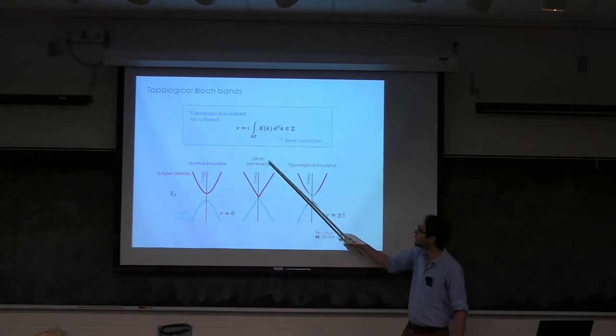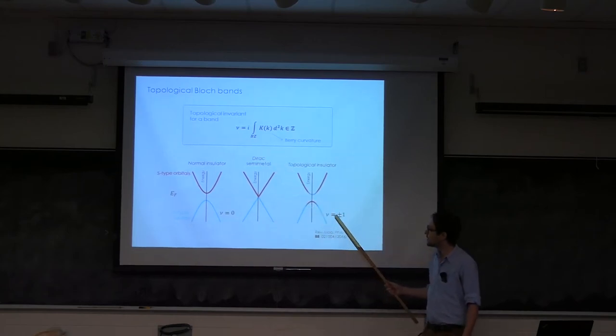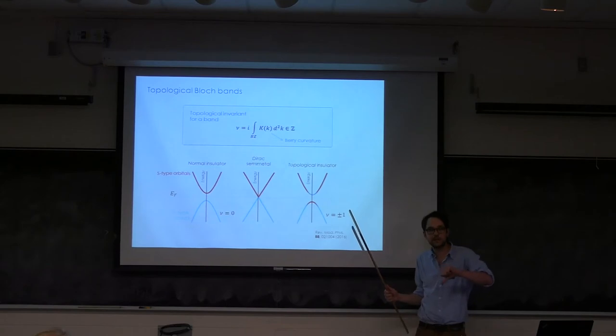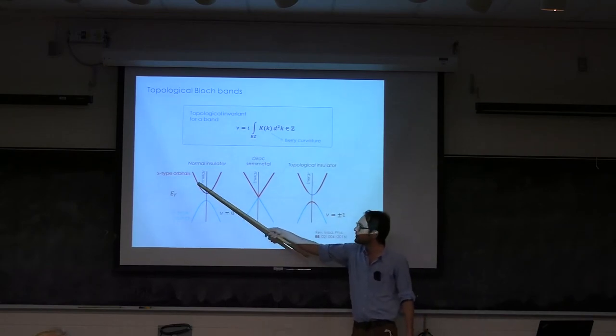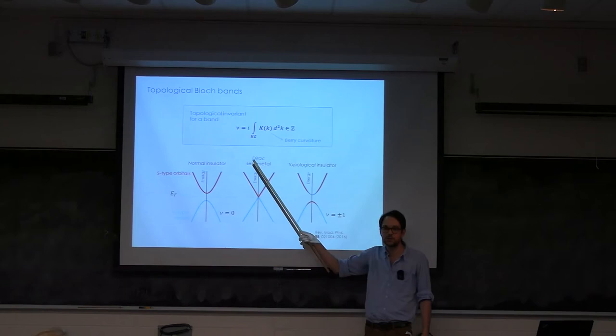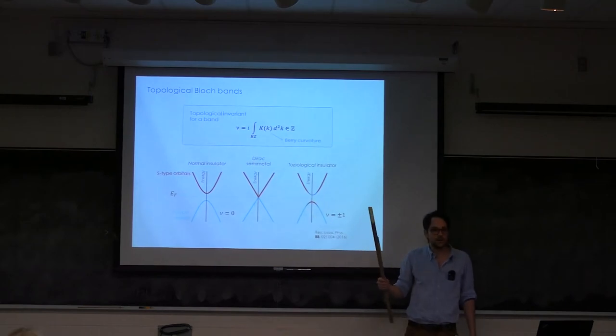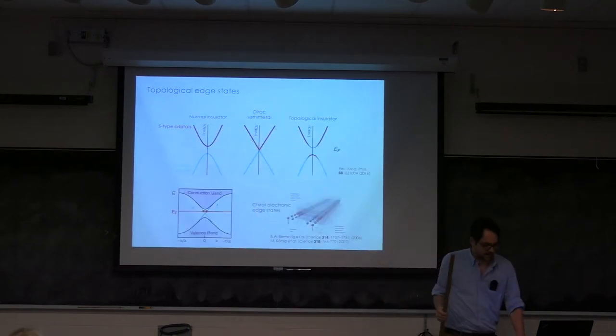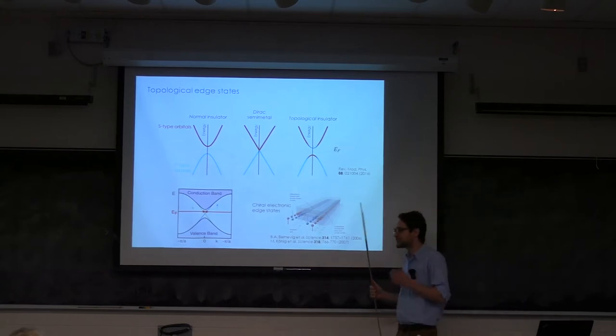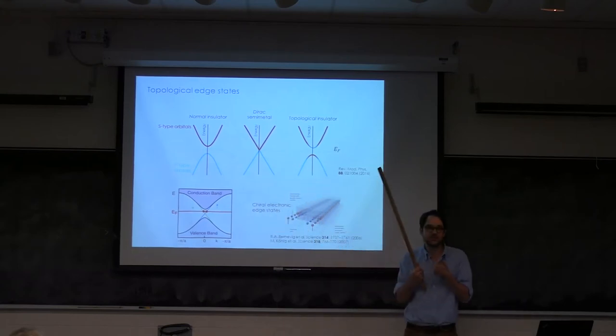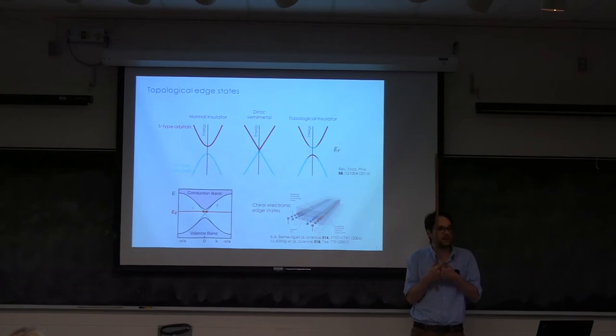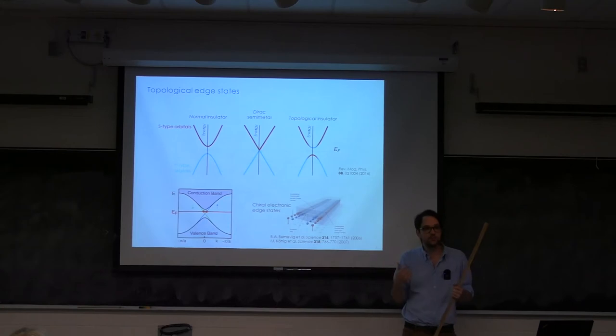And so if we were to calculate nu for this case, we would have plus or minus one for spin up or spin down electrons. And in this other case, because we don't have any winding of the symmetry properties, we end up with a trivial value of zero for nu. And all of this, most of the interesting physics occur when you put in contact two of these different materials, two of these insulators. So as I said, the only way to change the genus number before was to poke a hole. Now the only way to change the Chern number is to open a gap and close a gap and reopen it. All right.